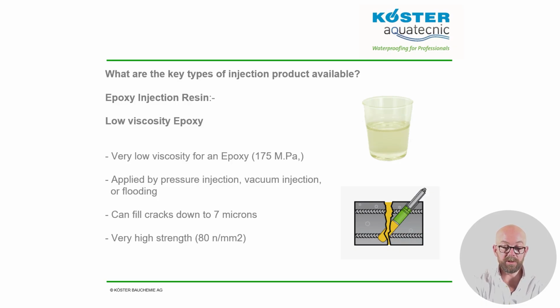This type of low viscosity epoxy also has very good adhesion even to damp concrete and cures to a strength of 80 newtons per millimetre squared, so can fully restore the structural integrity of the concrete.